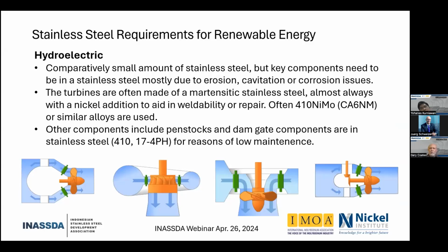The turbines are often made of a martensitic stainless steel, usually with a nickel addition, which helps in the weldability or repair. So a grade called 410 nickel moly, or the cast equivalent is CA6NM, or similar alloys are used. The company I used to work for had a martensitic ferritic austenitic alloy, a triplex, if you want to use a name for that, which was a weldable grade that was used in Francis turbines.